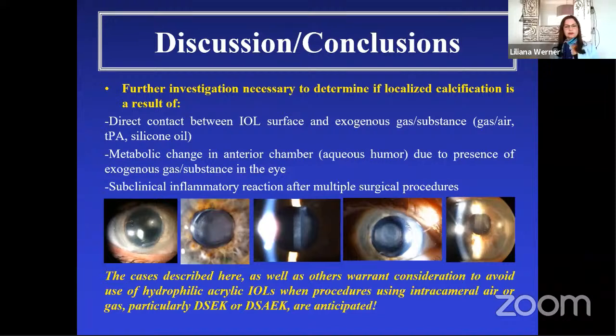We recommend that, in case you have a patient to be operated on for cataracts and you anticipate that a procedure such as the DSEK or the DMEK will be necessary later, you avoid implantation of hydrophilic acrylic lenses. Some clinical studies demonstrated that this type of calcification may occur in up to 10% of the cases.